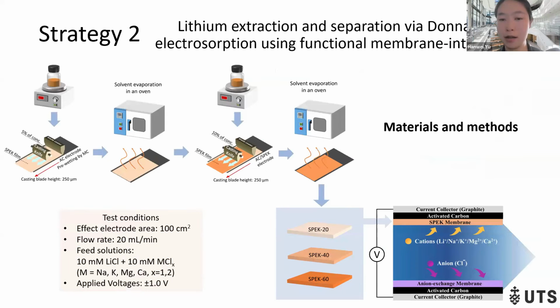So in the second research work, I used the second strategy, enhancing the lithium selectivity through the Donnan effect by integrating a functional membrane onto the CDI electrode. To implement this approach, I fabricated a series of sulfonated membranes called SPEK membranes and coated them on the commercial AC electrodes. The sulfonated groups on these membranes introduce fixed negative charge, which can facilitate selective adsorption via the Donnan exclusion mechanism. Three types of SPEK membrane based on their sulfonation degree were fabricated: SPEK-20, 40, and 60. The test conditions followed the same way as the last research.